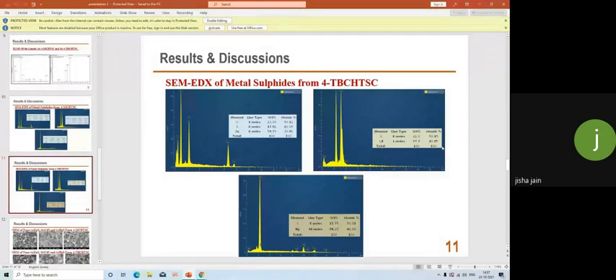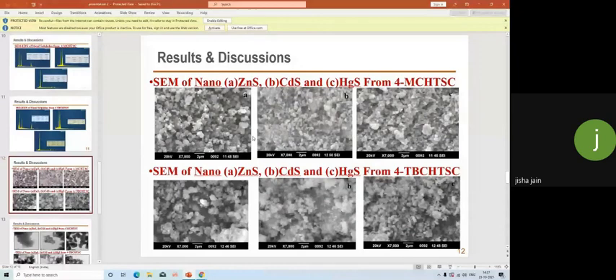In the case of cadmium sulfide, the nominal ratio between cadmium and sulfur is almost maintained in the crystal structure. In the case of mercury sulfide, here also a metal deficiency defect is seen. From the SEM pictures of all these metal sulfides formed, it is clear that most of the particles are homogeneous in nature. Better distribution of the particles is also seen, and it shows clearly an increase in surface area at the nanometer regime. The crystalline nature of the particles is also clearly seen from the pictures.